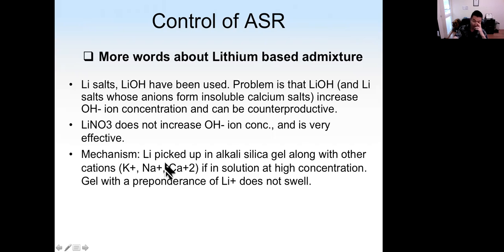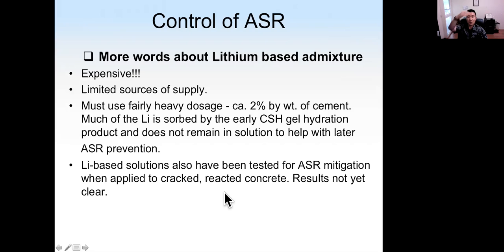Okay, and the reason for that is lithium will exchange other types of ions such as potassium and sodium and calcium. And the gel with lithium will not swell. So no swelling, no cracking. And the cost of lithium-based admixtures will be expensive, and we have to use a heavy dosage, so that will further increase the cost for lithium-based admixtures.